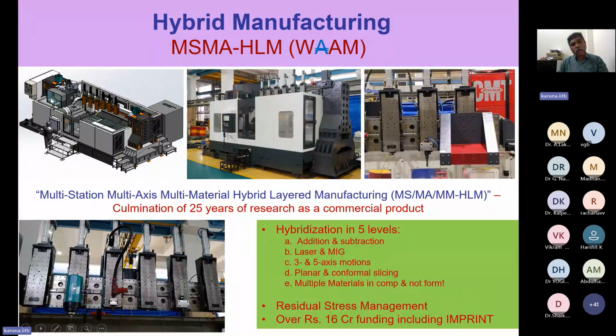So this is a very composite machine with several tool heads. It can do material addition and subtraction. It can have at least three different cladding heads, laser, MIG and TIG. And it is a full-fledged 5-axis system. Therefore, we can avoid the support mechanism. That is our third hybridization. So we have 3 axes as well as 5 axes on the same machine. On the same machine, we have laser as well as arc. On the same machine, we can build the part in horizontal layers or it can be conformal.